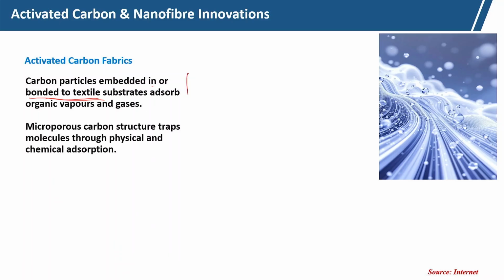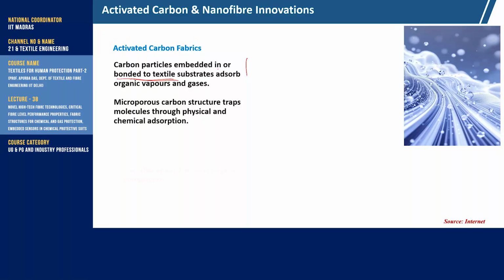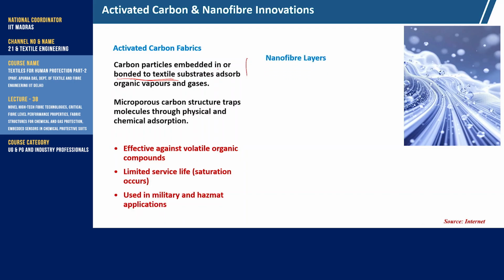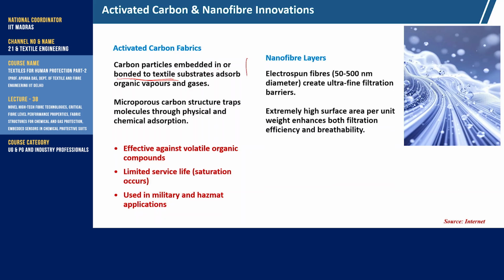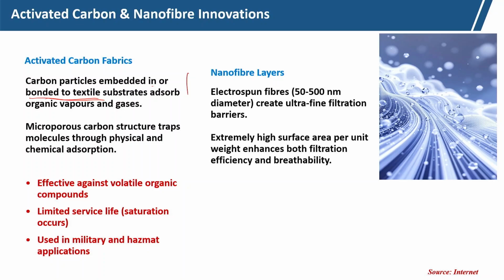So, the microporous carbon structure traps the molecules through physical and chemical adsorption. So, these activated carbon fabrics are effective for volatile chemicals. And nanofiber layers are also used on the substrate, with diameter typically 50 to 500 nanometers, creating an ultra fine filtration barrier, which prevents the chemical from penetrating.